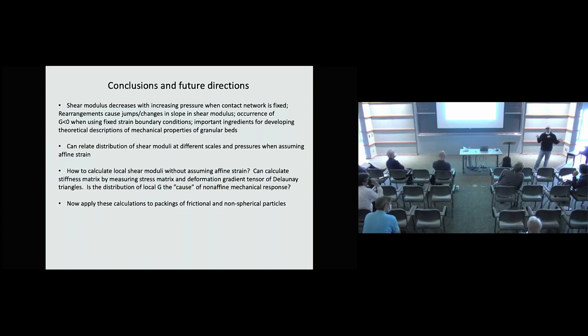I can do those. But you can also just say, I'm going to control the position of the boundary, and I'm going to apply whatever force is necessary to fix it there. If you do that, you'll generically get negative shear moduli, because the problem with negative shear moduli is it's unstable. It can run away, but I fixed it, so it by definition can't.